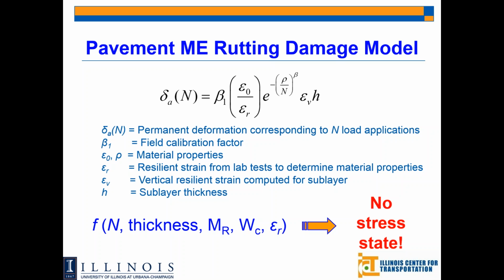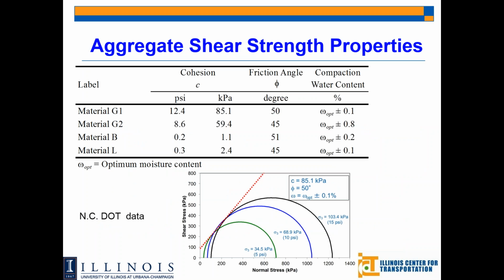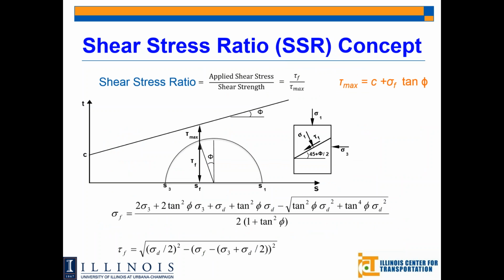I don't think you can predict permanent deformation without taking into account stress. This is a summary of some of the early work he did for North Carolina DOT, a range of values. They did shear strength testing, characterized materials, as well as modulus testing. Now here's the factor that you really need to keep in mind, shear stress ratio. Stress ratio is a most important parameter when you start predicting permanent deformation of granular materials.